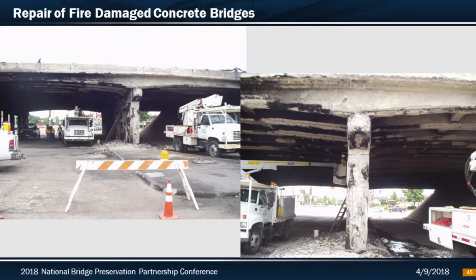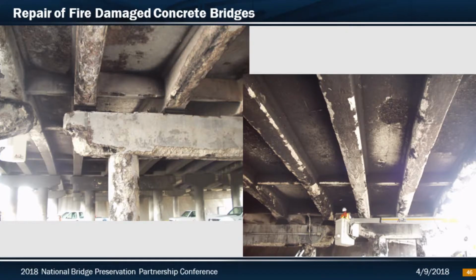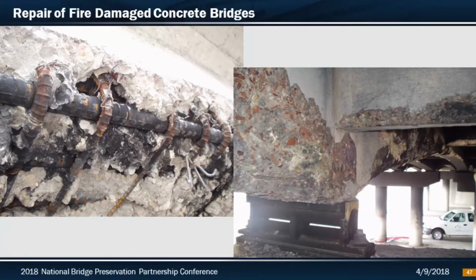Moving on to some of the fire damage. This was a particular incident in '05 where a tanker truck went over the rail, slid under the bridge, caught on fire, burst into flames, and burned for a couple hours. It ended up damaging 5 beams and 3 columns. The whole southeast interior bent cap was severely damaged. Damage cannot necessarily be assessed because of all the smoke and discoloration, so we had to get in there and do a lot of chipping, removing all the unsound concrete to expose the layers of discoloration and find where it was sound before we could determine any repair methods.